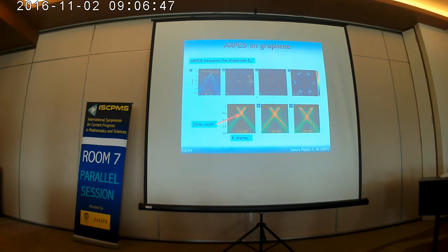And this is the angle-resolved photoemission measurement of the graphene. Indeed, researchers see that the conduction band and valence band show linear behavior. And the second way to identify this conduction and valence band with the linear dispersion is doing the magneto-optical measurement.